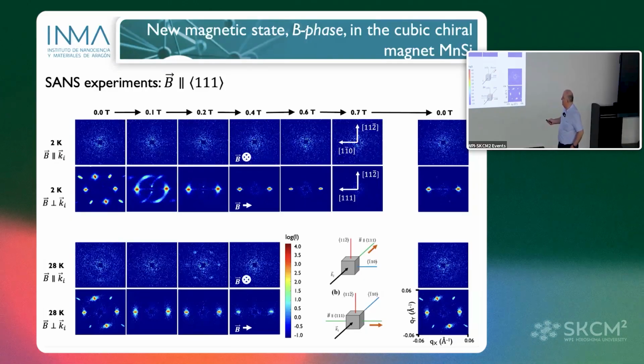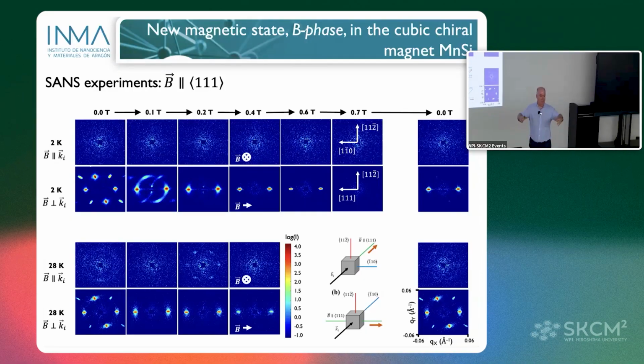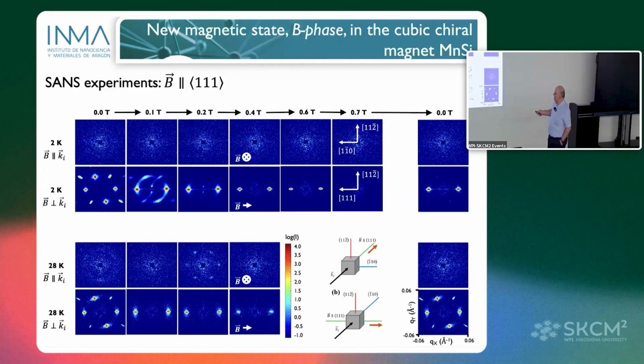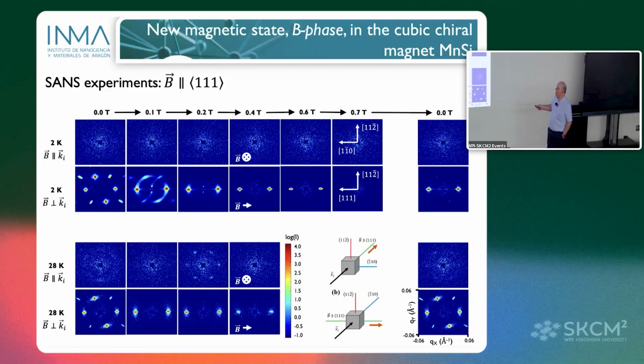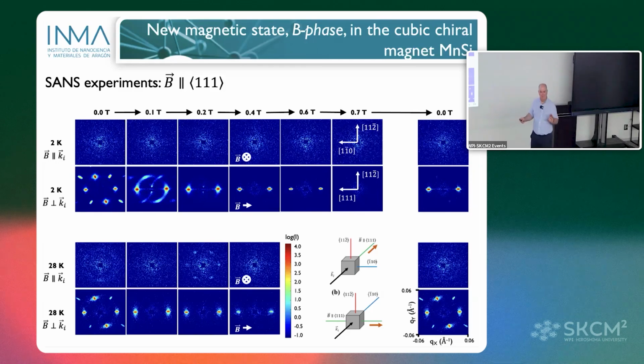And the intensity of these peaks increases because the size of the magnetic domain along 111 is increasing. Then the intensity increases and the other points decrease. You start now increasing the magnetic field and you start to close the cone. You have a helix, single domain crystal, and helix propagating along 111. You increase the magnetic field and you start to close the cone, then the intensity decreases, and in the ferromagnetic state, you don't have any intensity.